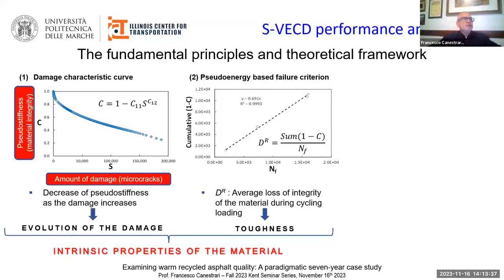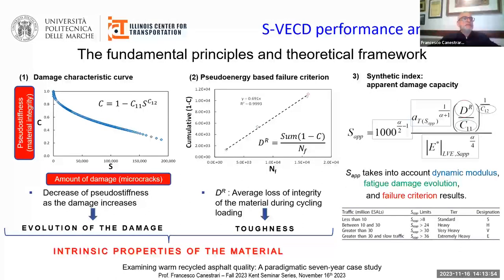Once obtained the pseudo stiffness curve, a pseudo energy based failure criterion is adopted to calculate the parameter Dr representative of the material toughness. The higher the Dr parameter, the higher the material toughness. Then all the experimental results are summarized in a synthetic index named SAP, representative of the apparent damage capacity that takes into account the dynamic modulus, fatigue damage evolution and the failure criterion results. The higher the SAP, the better the fatigue performance.